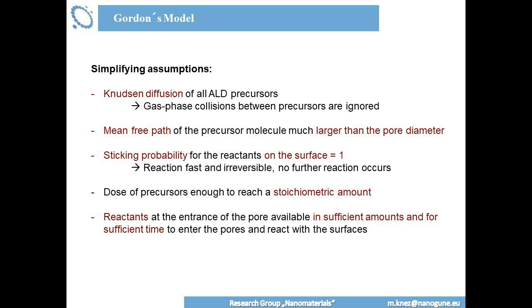So if we go to Gordon's model, it is a purely, let's say, simplified physical model. You think about the gases, you think about Knudsen diffusion. So you have the diffusion of the molecules and you have no collisions, so you just ignore collisions between the molecules. You think about the pore. The mean free path of the precursor molecule is much larger than the pore diameter. These are just simplifying preconditions. The sticking probability for the reactants on the surface is 1, which means if a molecule comes to a surface, it will bind instantly and irreversibly. That's the claim here, so it means you also simplify the chemistry.